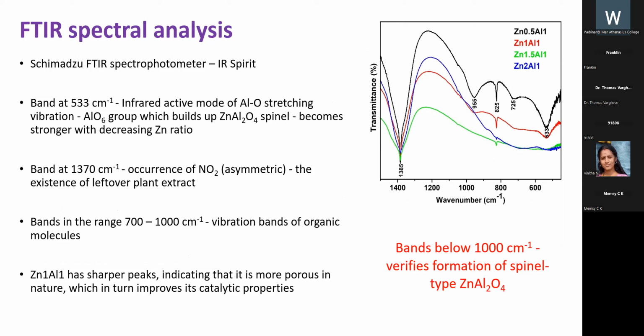To substantiate the XRD results, FTIR spectra were also recorded with the Shimadzu IRSpirit spectrophotometer, and there is a band at 533 centimeter raised to -1, which corresponds to the infrared active mode of Al-O stretching vibration, corresponding to the AlO6 group, which builds up the zinc aluminate spinel, and the peak becomes stronger with decreasing zinc amount. We can also see a peak at 1370 centimeter raised to -1, which corresponds to the NO2 group, which may be due to leftover plant extract, since our sample is not calcined. The bands in the range 700 to 1000 correspond to organic molecules leftover in the sample. And the samples with less zinc amount show much more intense peaks.